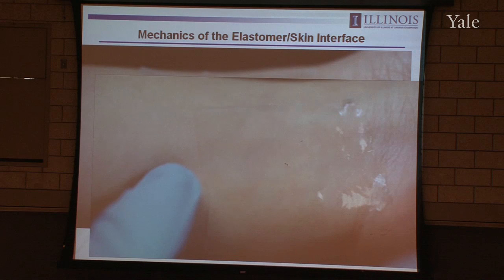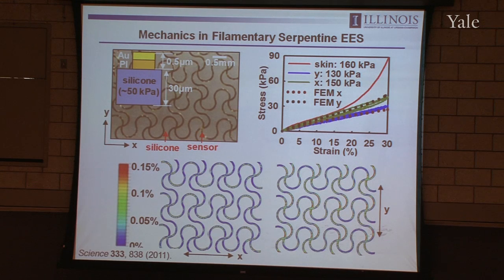Now, if you have arrived at a material that works in this way, the question is, how do you get a circuit on top of that without mechanically stiffening the system in a way that destroys that favorable mechanics? And it really comes back to ideas that I've already articulated, but implemented in a really extreme way. So thin, wavy, buckled, open mesh, but in this case, in the design of a filamentary serpentine structure. So very, very thin devices and structures in this kind of mesh, bonded to very low modulus elastomer. And if you do that, you can create an integrated circuit that has that characteristic. And then if you measure the stress-strain response, you find that this kind of circuit can be very quantitatively matched to the mechanical modulus of the skin.